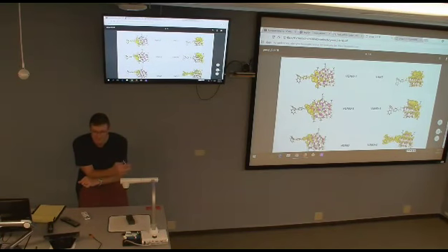But as I said, overall, Gaussian was not giving breaking of the molecule, but when it's really attached directly without carboxylic group attachment, like if you really align it so your carboxylic groups are too far away, because there are 2 in black dye, there is 1 isothiocyanate group, right? Or 2, also 2. So you really have to attach it with both. So actually in a solvent, it's just detaching from the surface. So it means it really doesn't want to be on a surface attached through the sulfur.